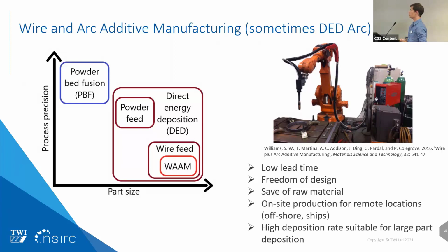The main difference between WAAM and other additive manufacturing processes that are more popular, such as powder bed fusion, is that WAAM uses a wire, so it is wire-based as opposed to powder-based. This allows higher deposition rates - for metals like steel, you can reach deposition rates as high as several kilograms per hour. It also uses a shielding gas thanks to the welding torch, so you don't need an enclosed space to build your part - you can do that in open air. Combining those two advantages, you can build large parts.